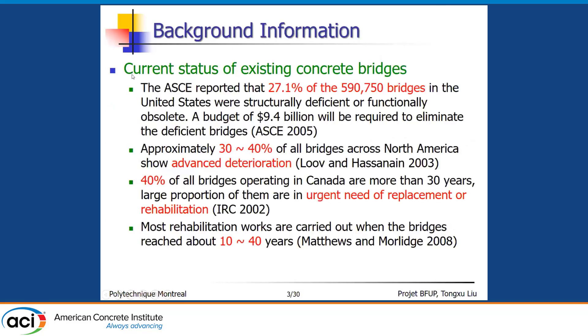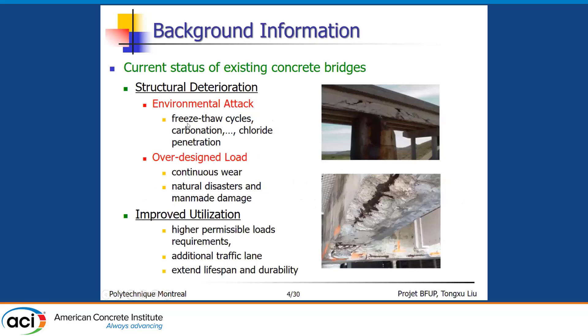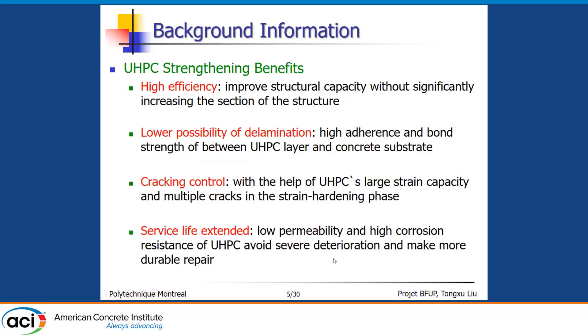The background information is mainly about the current status of existing concrete bridges. Several studies have indicated that a substantial number of bridges are structurally deficient or show advanced deterioration, in urgent need of replacement or rehabilitation. Bridges needing rehabilitation mainly stem from two reasons: structural deterioration from environmental attack — like freeze-thaw cycles, carbonation, or chloride penetration — or over-designed loads, or simply the desire to improve utilization, such as higher permissible loads or additional traffic lanes. So our research focuses on using UHPC to repair and strengthen concrete bridges.